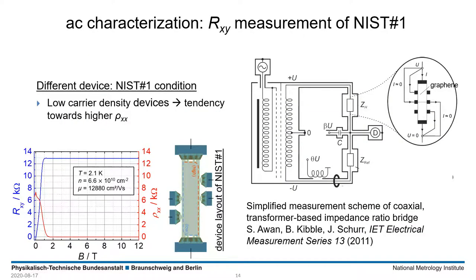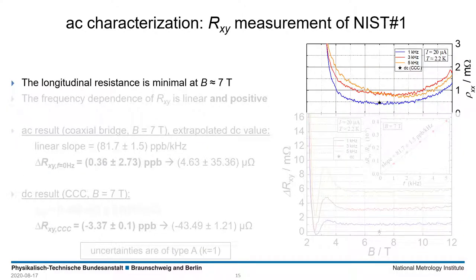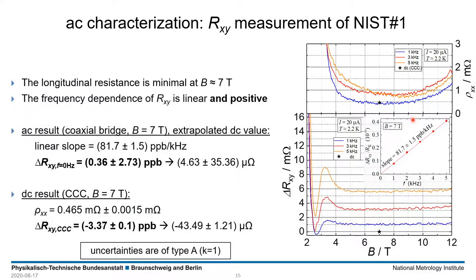In the following slides, I would like to show R_XY measurements with J. Schurr's transformer-based coaxial impedance bridge. These measurements were obtained with another graphene device named NIST-1, which uses the same layout as the previous one but has a significantly lower carrier density. This resulted in the beginning of the resistance plateau around 1 tesla. For this sample, the longitudinal resistance was relatively high with a minimum at around 7 tesla, with a DC and AC value of about 500 µΩ, which is expected for such low charge carrier densities. The ΔR_XY data from the impedance bridge describes the offset of the measured value from the expected value, which is half of the Klitzing constant.